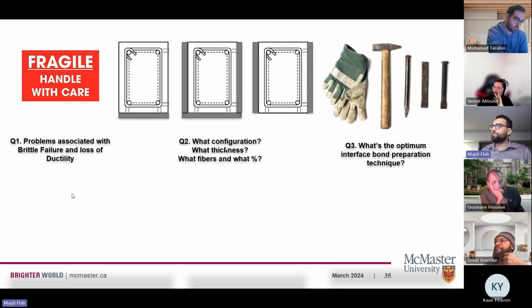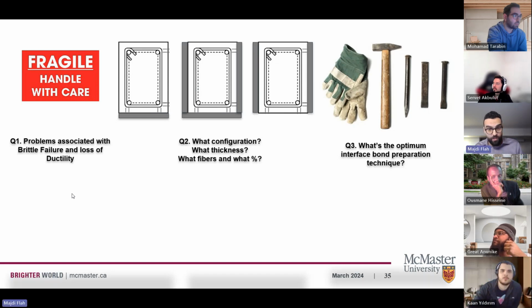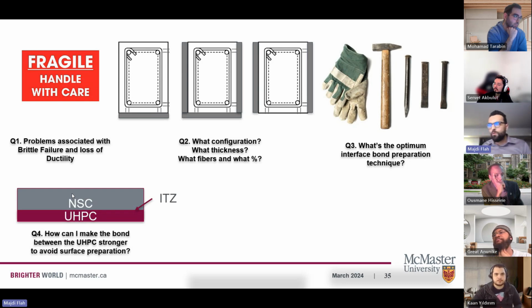The second thing is basically what configuration? Is it only top or bottom or sides or U jackets? What's the thickness? Is it 25, 50, 75? What fibers? And also at what percentage? Then, what's the optimum interface bond preparation technique? Every study you see, sandblasting is the best. Epoxy adhesive is the best. But can we provide a rational way on how to provide an optimum interface bond between the UHPC and the normal strength concrete? And then, how can we make the interfacial transition zone between them stronger?